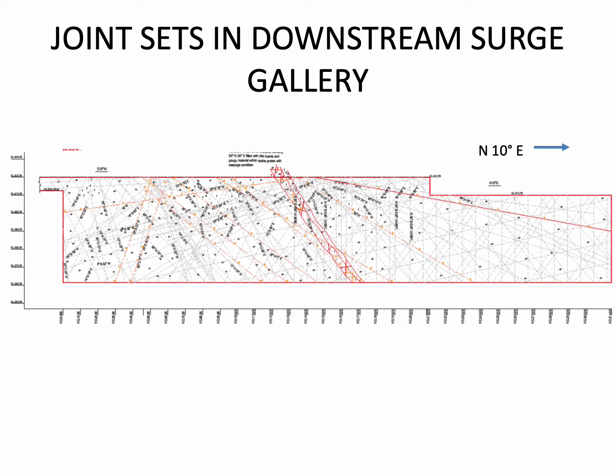This diagram shows that the downstream surge gallery is oriented north 10 degree east, and this is the shear zone, 3.5 meter thick shear zone, which traverses from the crown all the way in its walls at an angle of 55 to 65 degree. And these are the various joint sets which make the rock very blocky here, highly blocky here, with their joints filled with clay and fractured rock mass. This rock mass is lying over this sheared plane and making this reach of the downstream surge gallery vulnerable or problematic hanging wall.